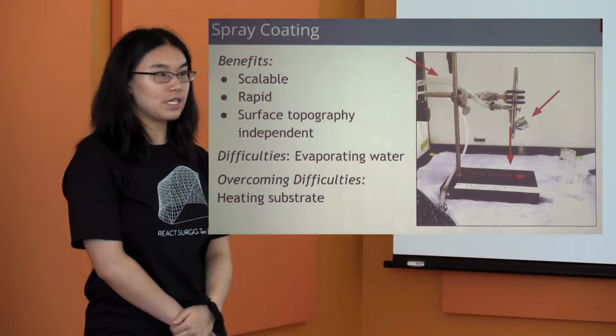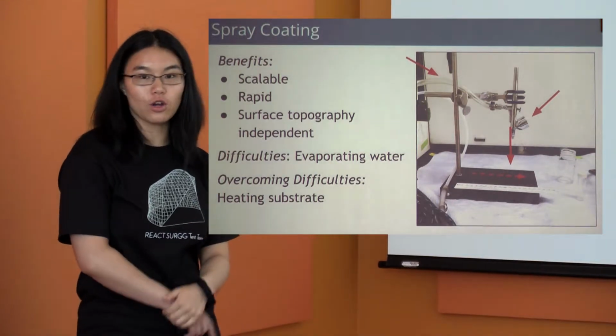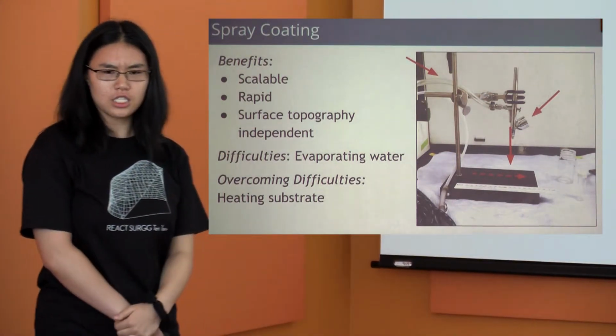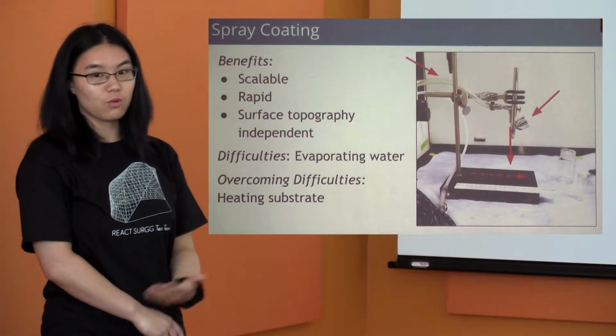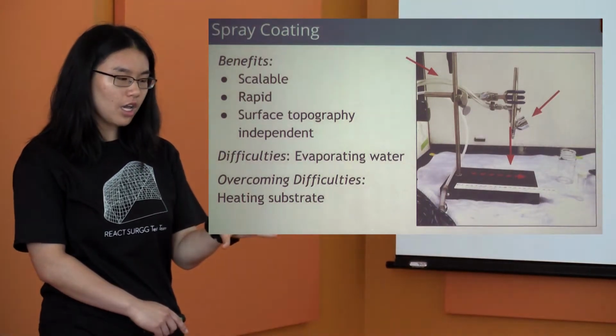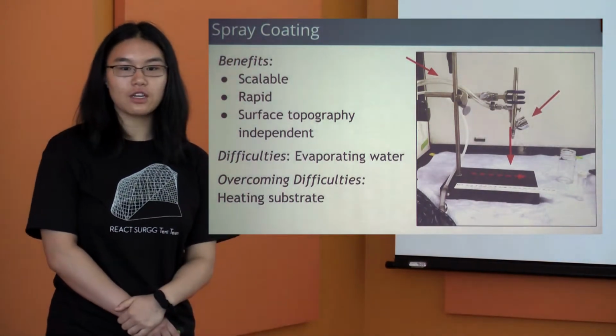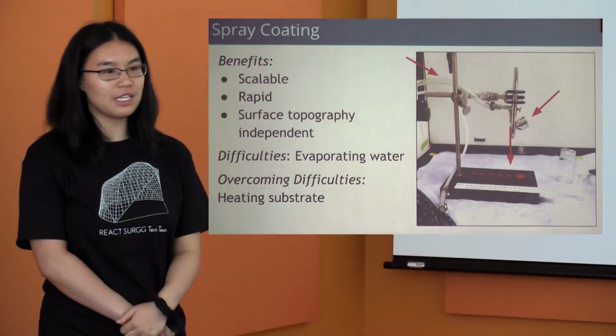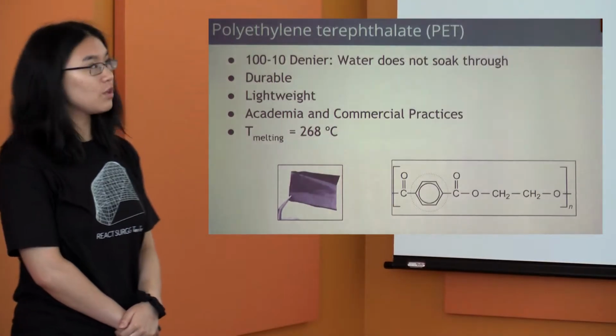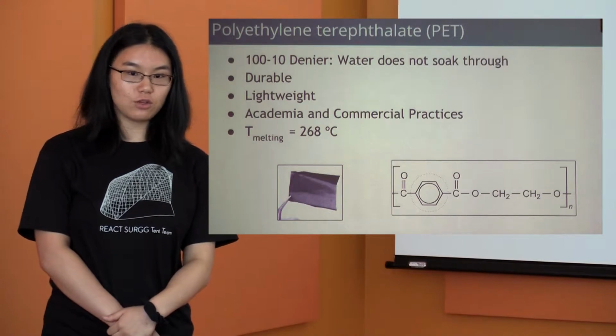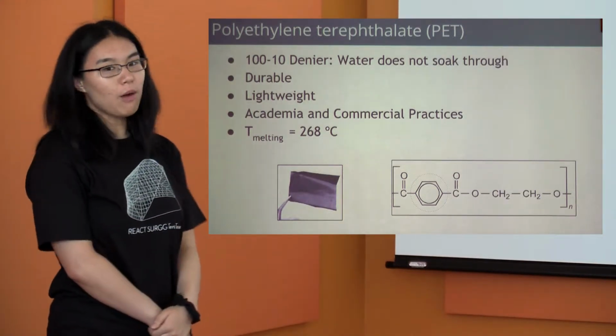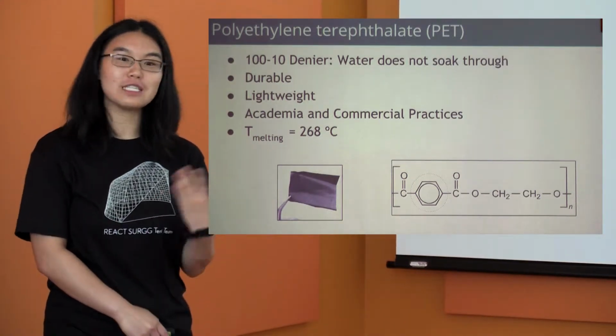Some difficulties that we did encounter: we used a water-based salt dispersion, so we had to evaporate water, since it doesn't actually evaporate immediately, which causes a coffee ring effect. In order to overcome this, we simply heated the substrate. Now, in conjunction with our characterization and design team, we chose the substrate in question to be polyethylene terephthalate, also known as PET.